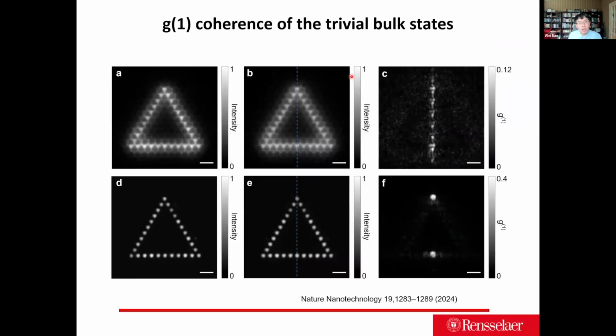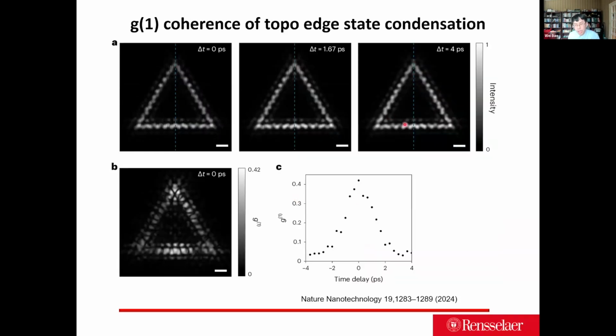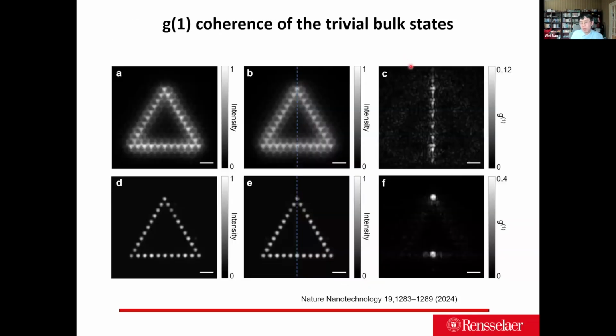So I want to show that the G1 coherence on the trivial bulk state, if you have just a trivial bulk state with no topological edge, you will see they only show the G1 coherence on the self-interference part, and the mode is highly localized without the propagating nature, compared with the topological edge. So essentially, once it runs purely into condensation, the whole topological edge behaves like one particle and shares the same coherence.